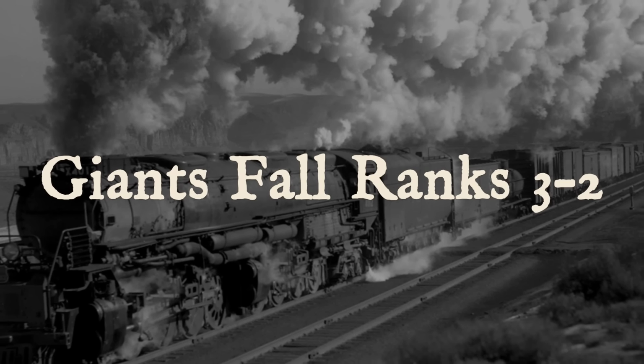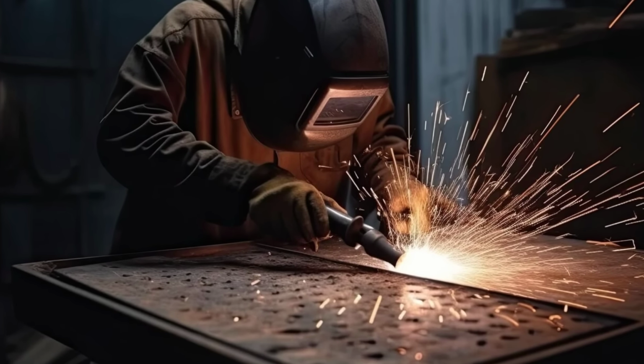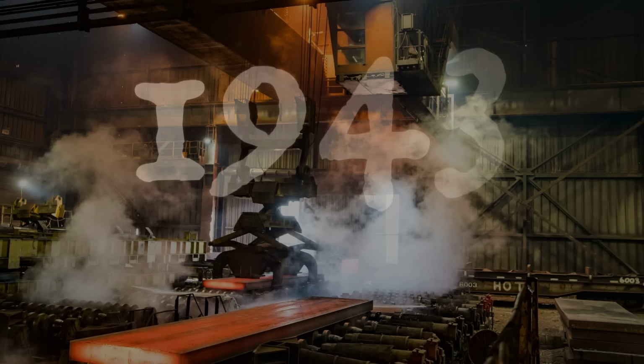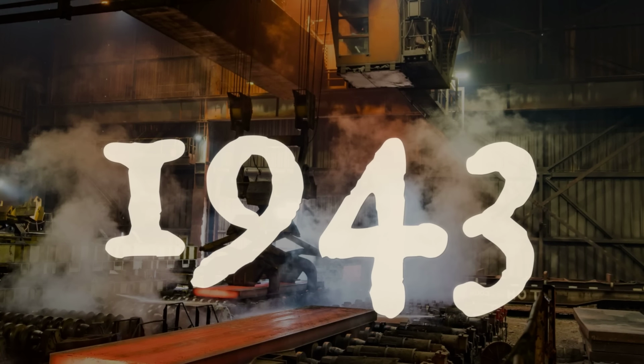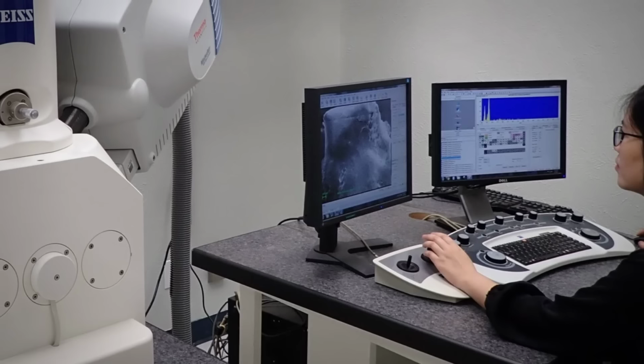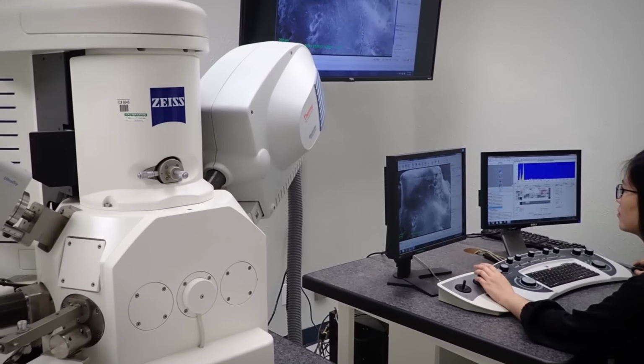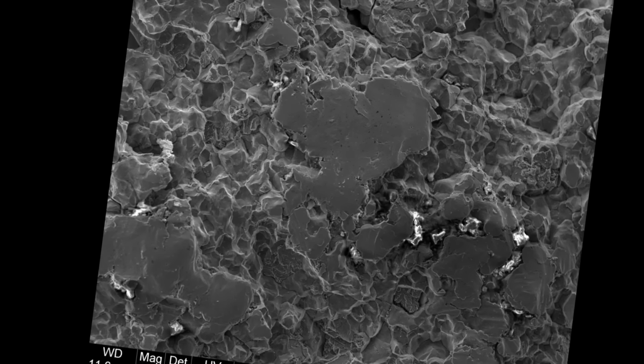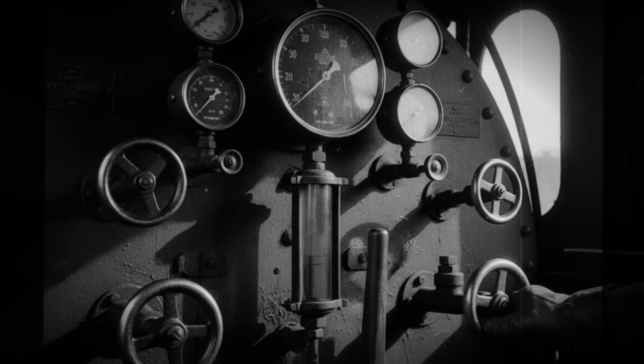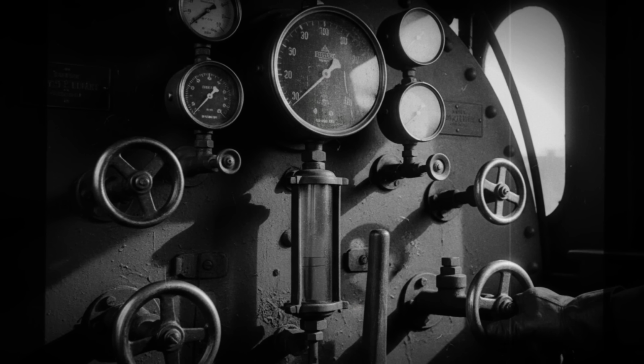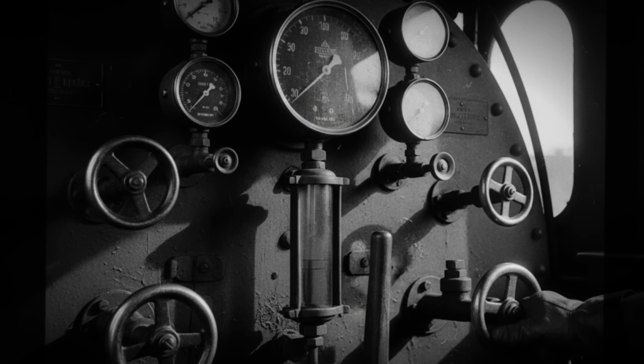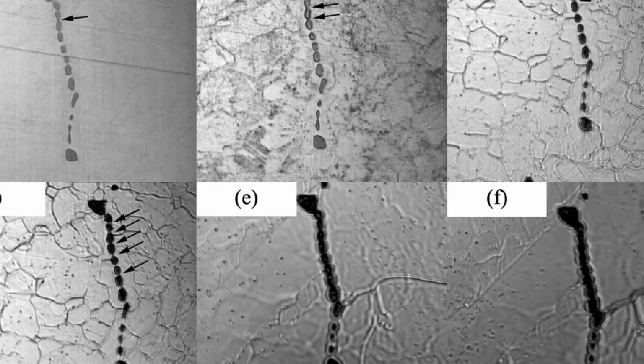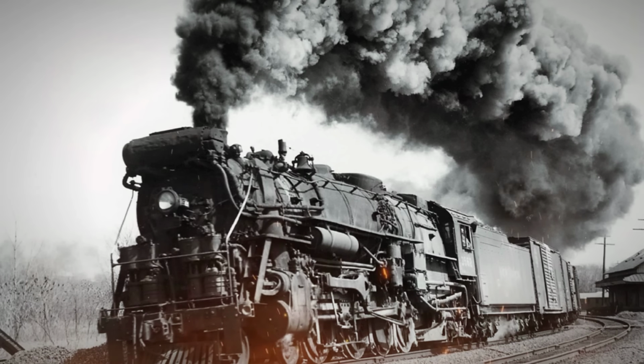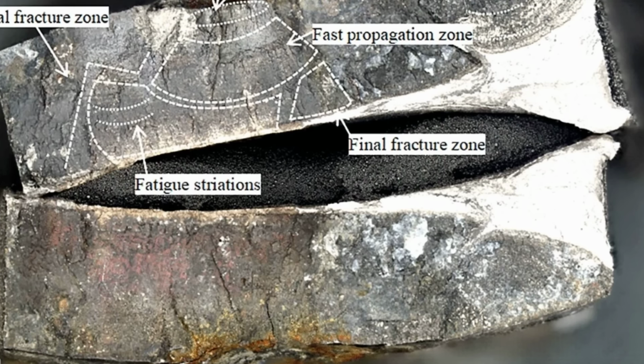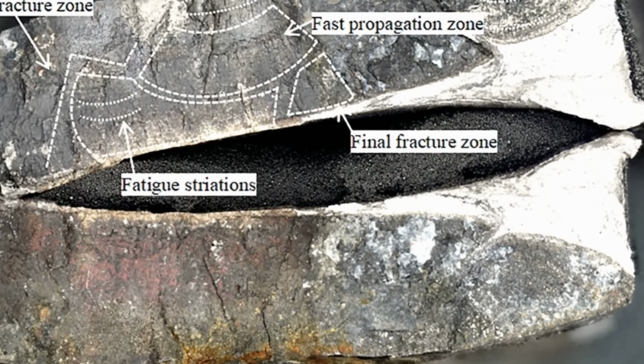Steel, in theory, is the fortress wall, but metallurgy is not theory, it is a game of atomic dice. A locomotive boilerplate rolled in 1943 might look flawless to the naked eye, but under the microscope, the story changes. Embedded in the grain, a manganese sulfide inclusion the size of a pencil tip becomes the future epicenter of disaster. Every pressure cycle, hundreds per hour and thousands per shift, works that invisible flaw, driving microcracks deeper along the boundary. Each firing, each throttle pull, flexes the lattice until the crack propagates far enough to threaten the vessel's integrity.